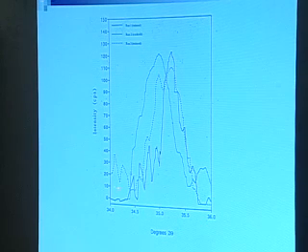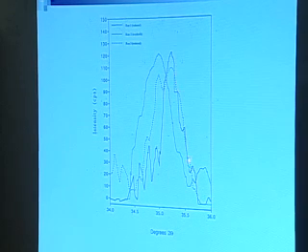But here's the idea. This is a scattering peak when you have the iron in the reduced form. Here it is when you have it in the oxidized form. So in other words, there's the direct evidence. The lattice parameter is expanding and contracting as I oxidize and reduce it. And this one, in this particular case, with 2 peaks broadened out, is in a form where it's sort of a 50-50 mixture.